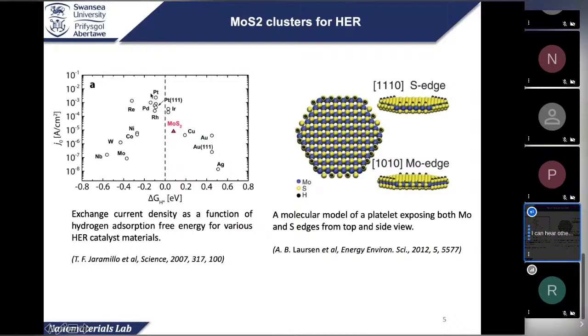At the moment, platinum is the best catalyst for this reaction, but the problem with platinum is that it is expensive and scarce. So people are trying to look for different materials to replace platinum, or decrease the amount of platinum in the catalyst. Here we select MoS2, which has a very low free energy of hydrogen adsorption, but the problem is the activity is not as good as platinum. So we're trying to increase the activity of pure MoS2, to shift the position of MoS2 upward a bit.